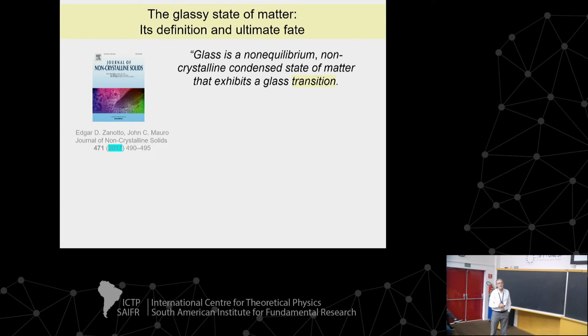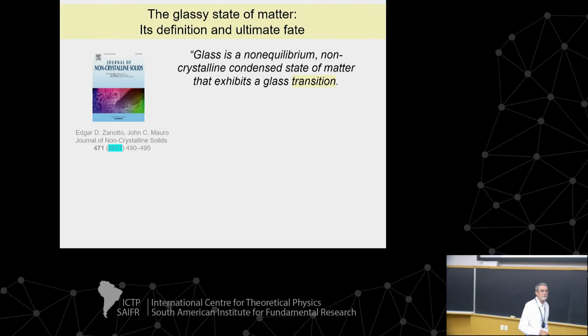Can I have a water glass? Yes. People have made glassy water. You have to cool it very fast, with a cooling rate of 10 to the power 10 Kelvin per second or so. Tiny droplets of water become glassy. There are many papers on glassy water. Is this what we do when we run cryo-TEM, when you have the amorphous water? Yes, so it's sort of a vitrification of water. Of course, water is known as a reluctant glass-forming substance.